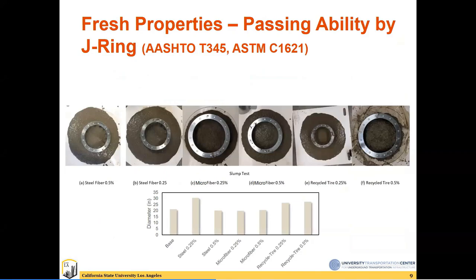This is one example of the passing ability results by J-ring, and you can see how different mixes could pass through the reinforcement of the J-ring test, and by measuring the slump flow, the slump spread, and the central height of the spread after the spread is done, we can evaluate the passing ability and workability of the SCC mixes.